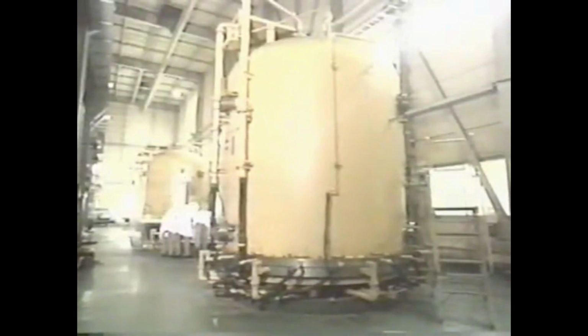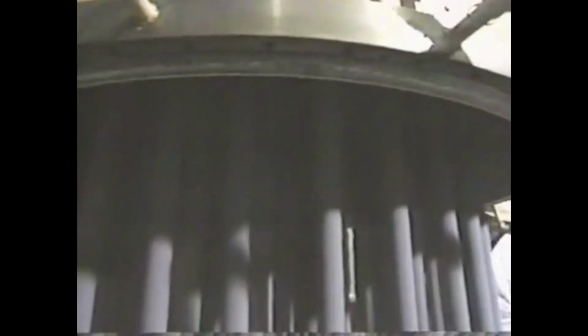This is a giant electric cauldron for making solid silicon out of the silicon gas. The technicians set approximately 100 silicon seed rods, which are cut out from manufactured products. Electricity is passed through the seed rods, while the silicon gas is continuously circulated for a full 5 days. During this time, the seed rods grow to a thickness of about 10 centimeters.